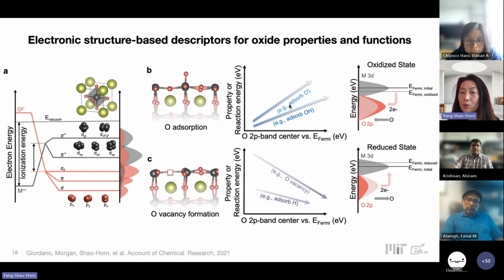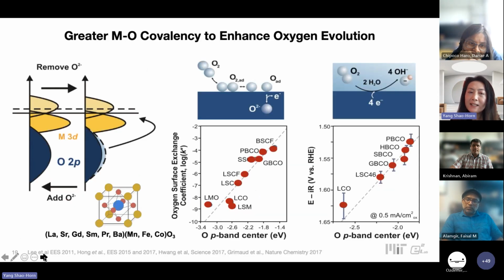On the other hand, if we adsorb a reducing species, we're essentially transferring an electron from the oxygen P band to the D states, and that driving force increases as we go to the late transition metal, with a higher oxidation state. And this is basically the correlation between the changes in electronic structure and the changes in the binding energy. And so utilizing this general concept, one can correlate the experimentally measured, let's say, surface exchange kinetics